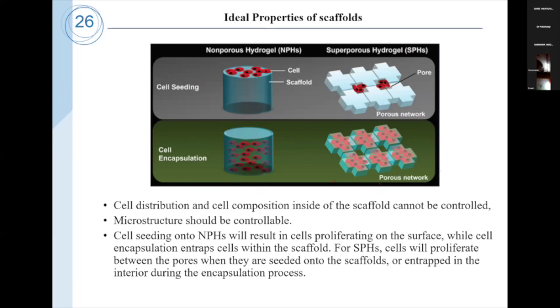However, the microstructure of the scaffold should be controlled, because if we seed cells on the non-porous hydrogel surface, the cells grow and expand on the surface of the scaffold only. Whereas if we encapsulate cells with a polymer solution and prepare the hydrogel, the cells are encapsulated within the hydrogel. If you see here, with cell seeding on the porous network, superporous hydrogel, cell growth is within the pore only, not on the surface of the hydrogel. Whereas when cells are encapsulated with polymer solution and the porous network structure is prepared, the cells are distributed within the network, not in the pore.